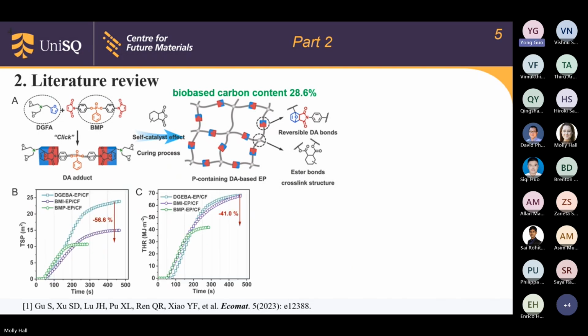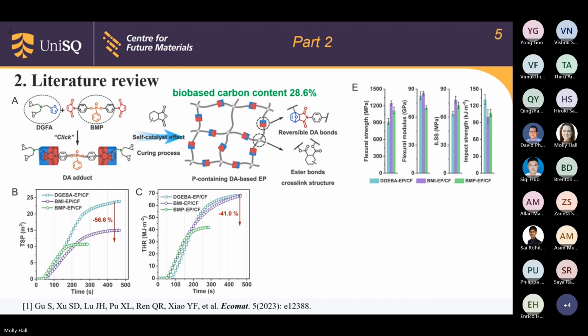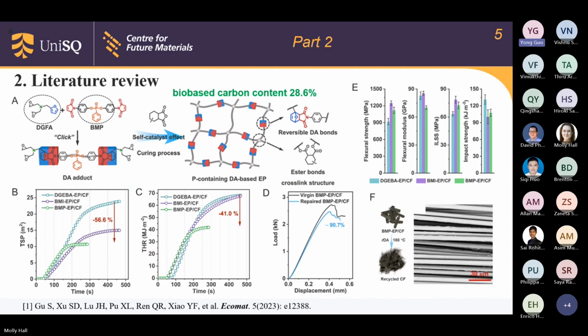First, this system achieved flame retardancy, such as the TSR decreased 56.6% compared with the commercial epoxy resin, and the CFRPs decreased 41% of the THR compared with the commercial CFRPs. And the mechanical properties were enhanced compared with the commercial one. Last, this system achieved repairability and recycling of the CF.